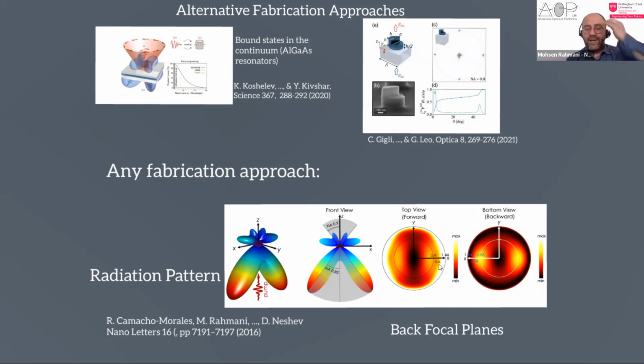And here are the back focal planes. The theory shows, the entire outer circle shows the entire nonlinear emission, while the inner circle shows what we can get with the microscope experimentally. So as you see over here, in the normal incidence we have really low signal, almost zero signal. So it becomes a problem because all the generated nonlinear signal goes to the side.